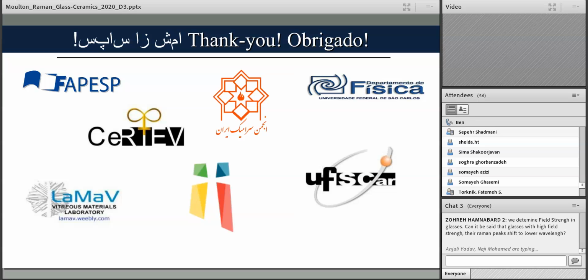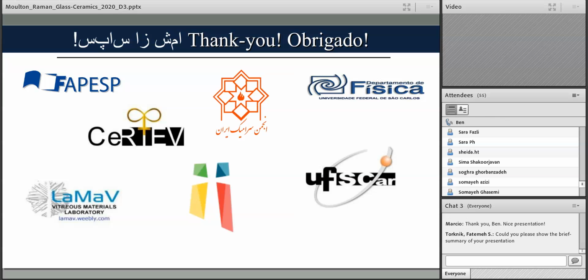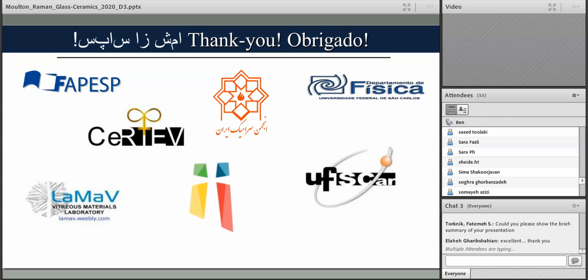Yes, as a first order model. Okay, sorry. The question is, we determine the field strength in glasses. Can it be said that glasses with high field strength have their Raman peaks shift to lower wavelengths? As a general comment, yes, the field strength is related to how strongly bonded the two elements are. And so, if you have stronger and more covalent bonds, you have a shift to higher frequencies. And if you have more ionic or weaker bonds, the bands will shift to lower frequency.